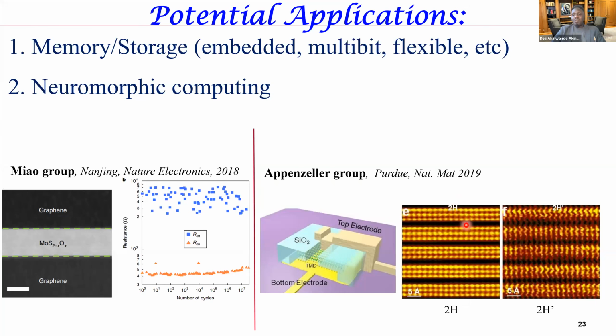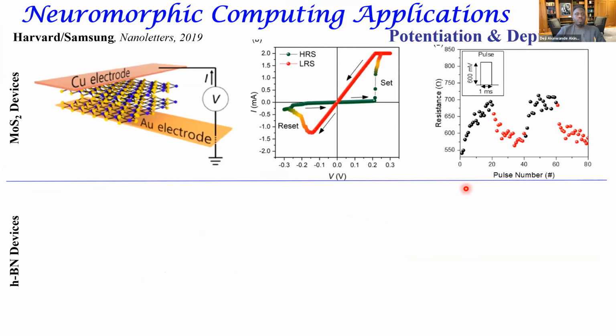You have this very nice van der Waals gap between the different layers, but under high voltage, you have some sort of phase change where it goes from this 2H to some kind of disordered 2H prime, where suddenly this van der Waals gap, according to cross-sectional TEM, doesn't look so clear. There seems to be some sort of interaction between the gaps. So anyway, there's a great interest to better understand this phenomenon as well, in terms of this quasi phase change phenomenon in certain 2D layers.